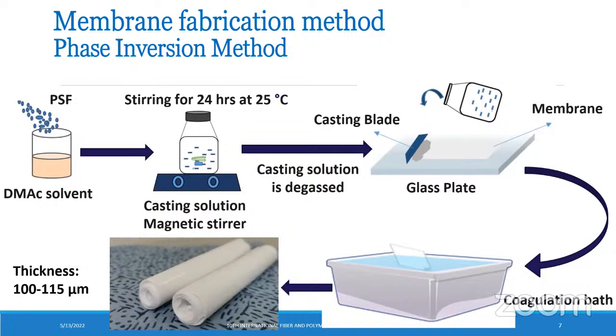Before membrane casting, the casting solution is degassed in a water bath at 25 degrees for 30 minutes to remove the air bubbles. The casting solution is then poured onto a clean and dry glass plate. The glass plate is immersed into the coagulation bath of deionized water, and after that, the membrane is stored in DI water.